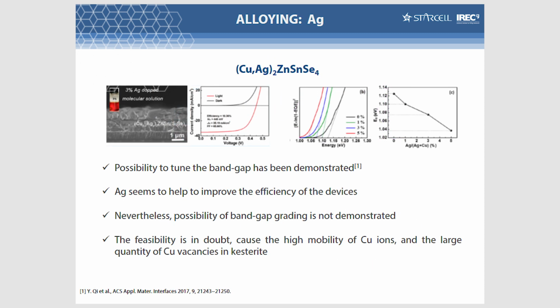Then it was demonstrated that with silver you can play with the band gap, obtaining quite nice efficiencies, but the problem is that we have to change drastically our solar cell device structure, because now we have an N-type absorber and not a P-type anymore. So this means that we have to really rethink our devices, and this, for the moment, can be a bit problematic in terms of the introduction of silver.